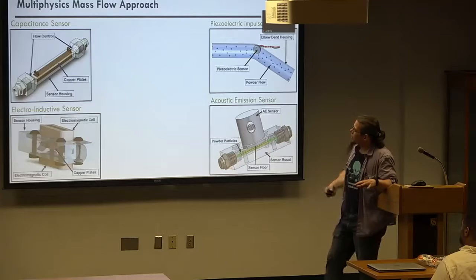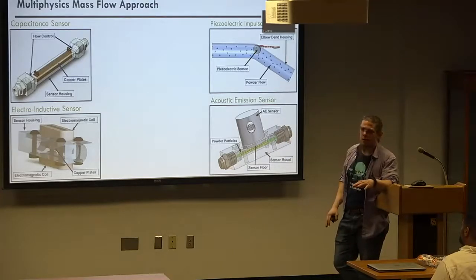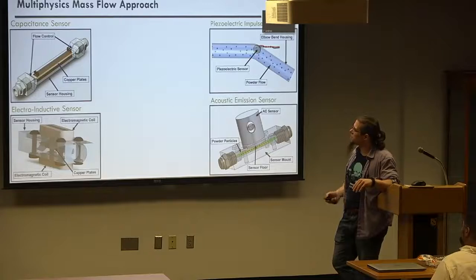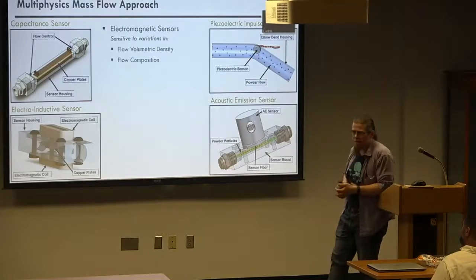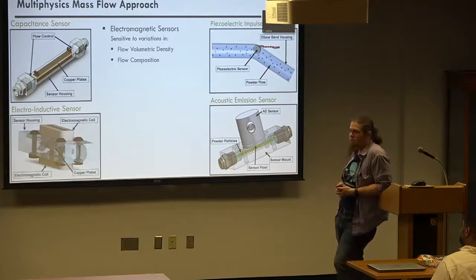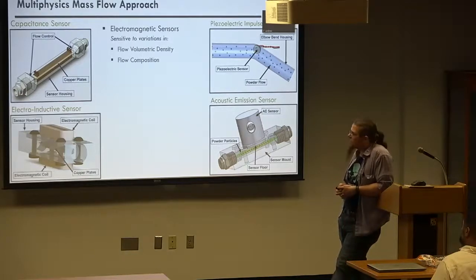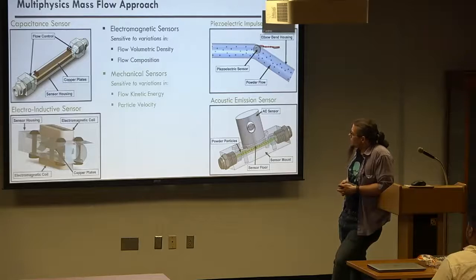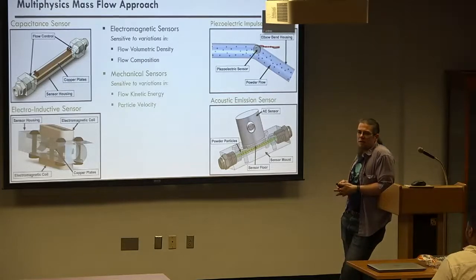All right. So, a more holistic approach, looking at all four here at once. We're looking at a multi-physics approach. We have electromagnetic sensors, which are sensitive specifically to the volumetric density of the flow, kind of your mass flow rate divided by your velocity. We have the flow composition. So if I change what the powder is, I'm going to get a different signal strength. So I can actually tell, or at least the hope is that we can tell, if we're flowing steel versus titanium, for example. The mechanical sensors on the right are sensitive to variations in the flow's kinetic energy and particle velocity specifically, right?